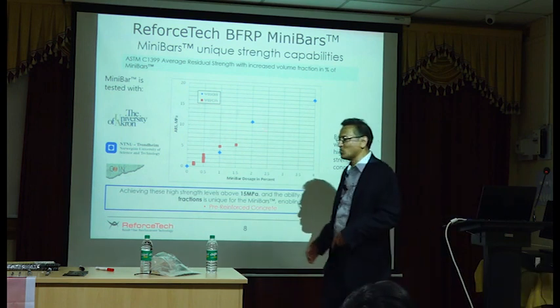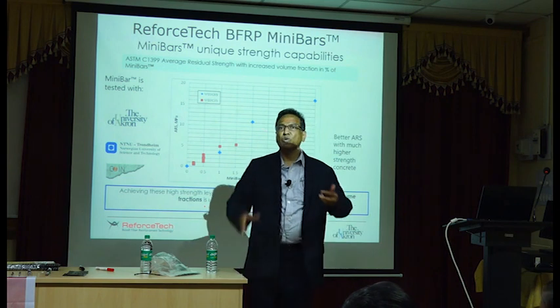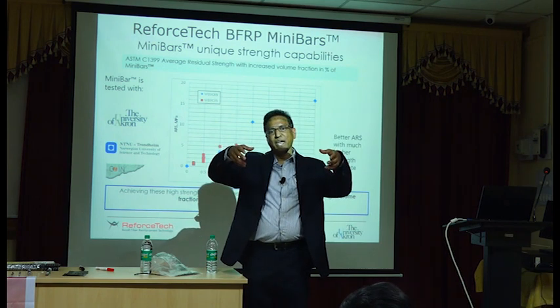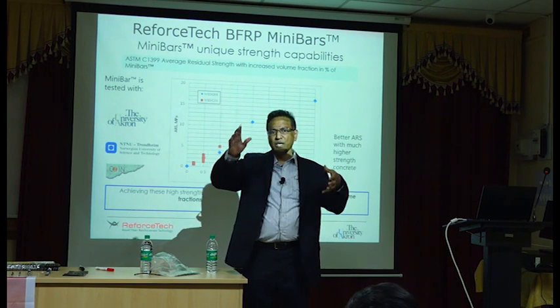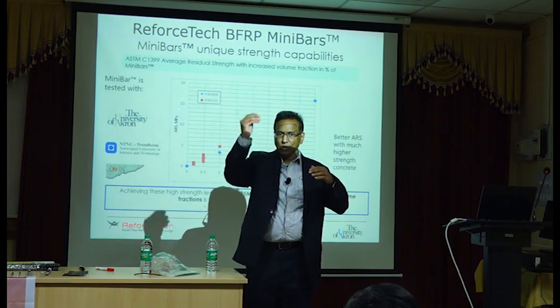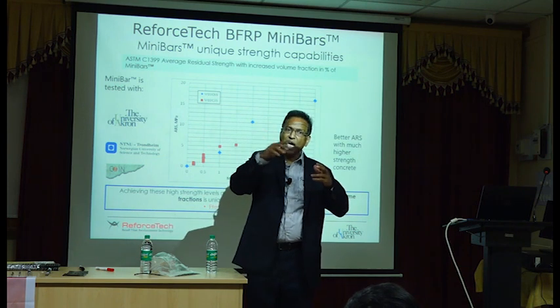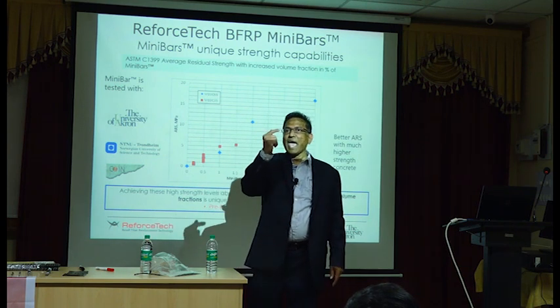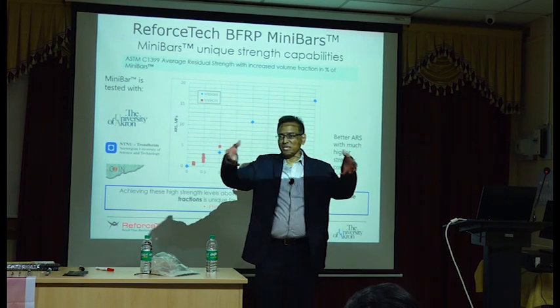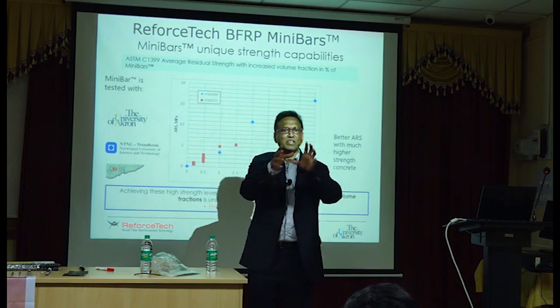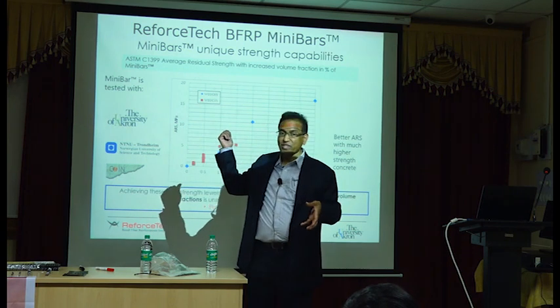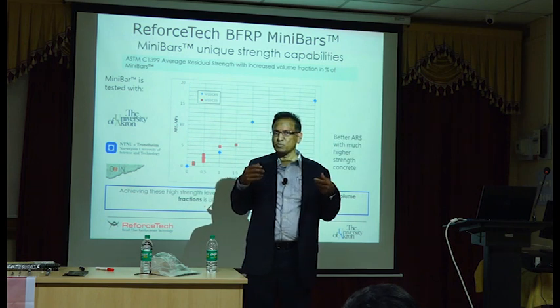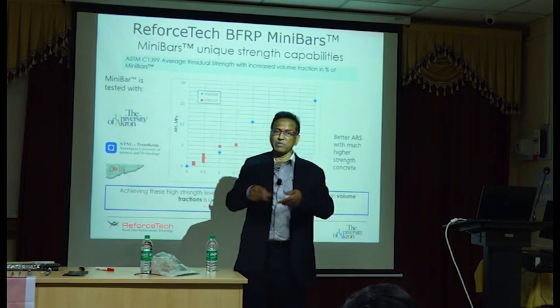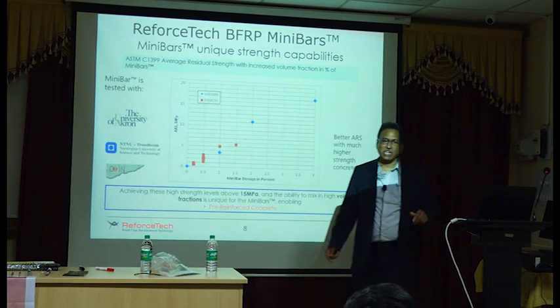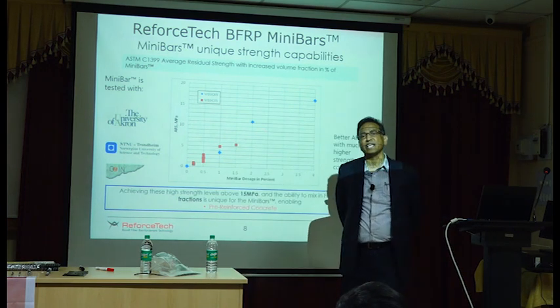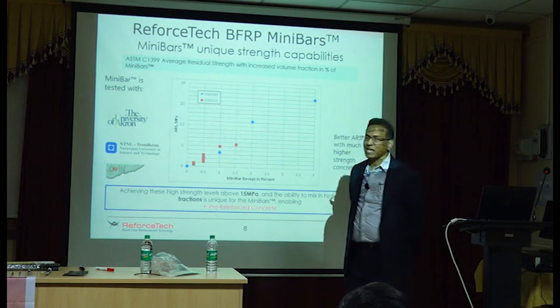The residual strength test is where you first crack the specimen, then release the load, and then you load it again after cracking. So after cracking, if you have no fiber, what will happen to the concrete beam? There will be two pieces. Whereas with fiber, even after cracking, they won't become two pieces. You can still apply load and it will still carry load. So that's known as residual strength. After cracking, whatever strength remains is known as residual strength.